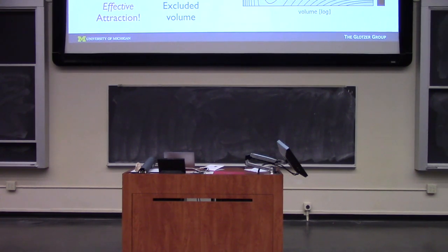These are what the van der Waals isotherms look like. At high temperature, your pressure versus volume is monotonically decreasing. You just go from high pressure, small volume, to low pressure, large volume, one phase. And below the critical point, now you have this inflection. That means that at one pressure, you have two volumes, two phases coexisting with different volumes, a high density phase and a low density phase.